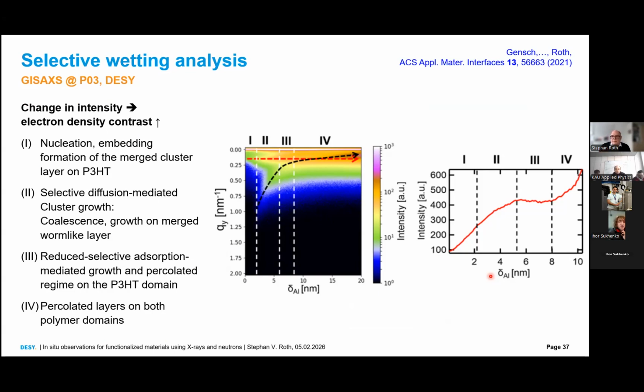Then I guess my question is no longer valid, because it was about how to preserve the structure of the deposited material. Very good question. Actually, we did this. We deposited polymeric material. When you sputter polymers, you cannot preserve the structure. You know that the target is, say, PTFE, and we deposit fragments of PTFE. So you have a polymer-like layer, but not the polymer layer. We did this in the past too, but for us, we want a template, which is our prefabricated polymer film, and then we deposit our metal layer on it.